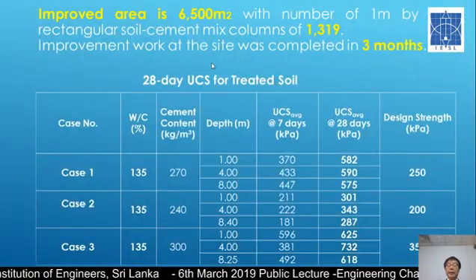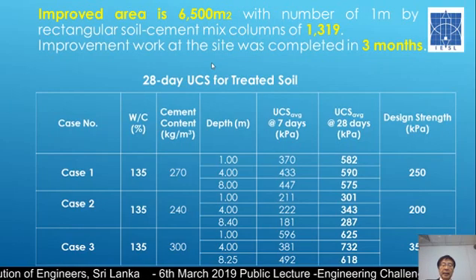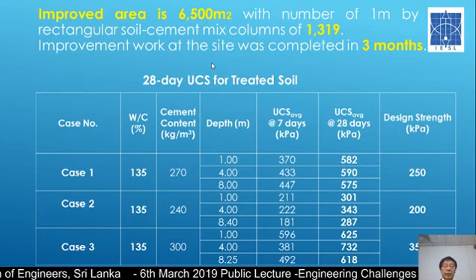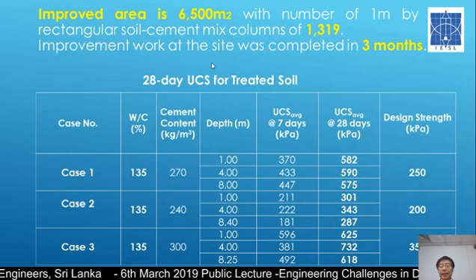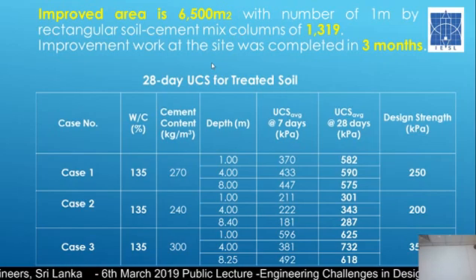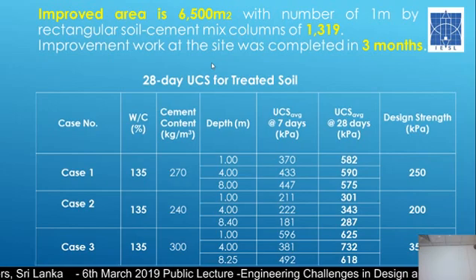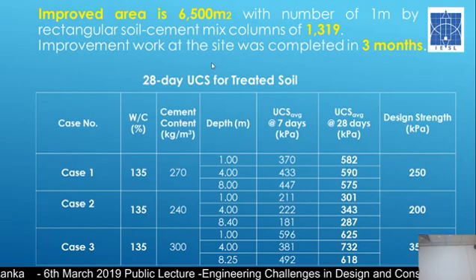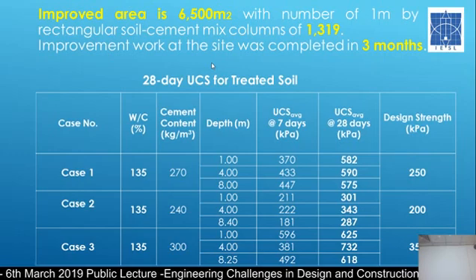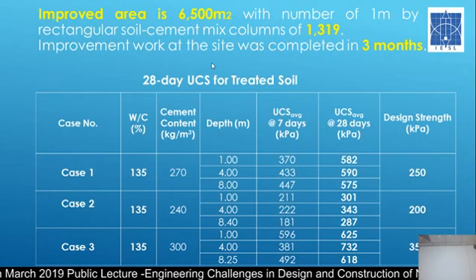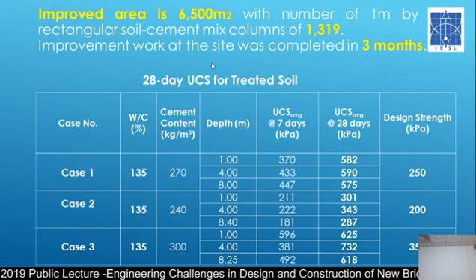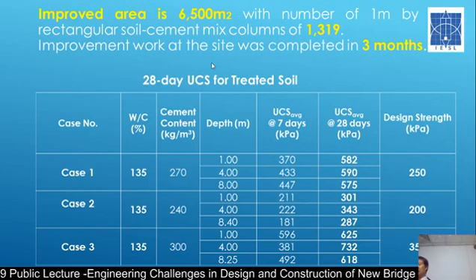So anyway, after several trial and error, we changed the water cement ratio to 135%. And then, as you see in that column, we finally got this strength, whereas the requirement is much lower. Also, you see that these 3 columns indicate the depth of the soil: 1 meter, 4 meter, 8 meter. So in the different soil depths, the strength we obtain is very similar, which means it is uniformly mixed for the entire depth.